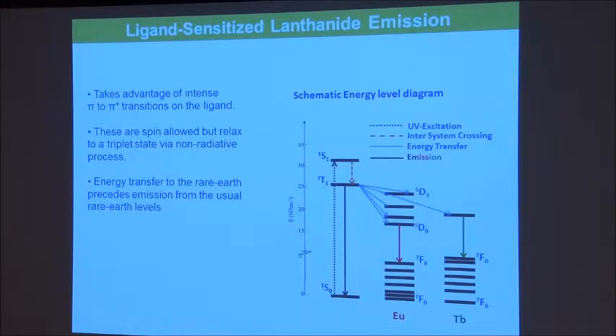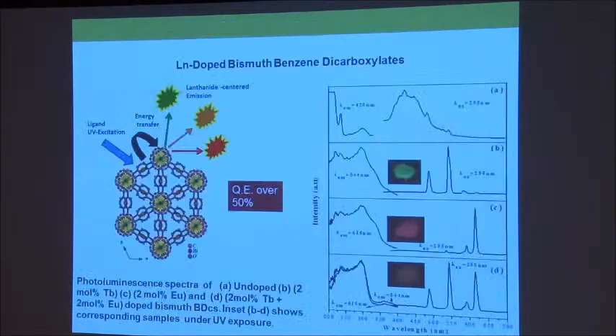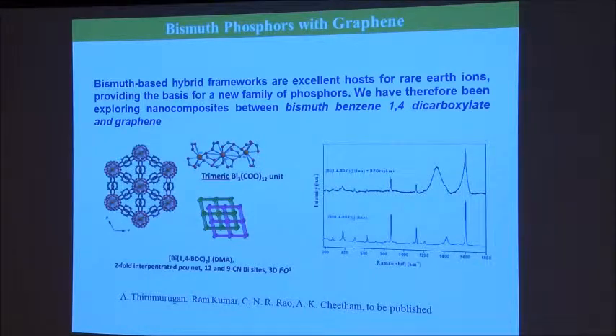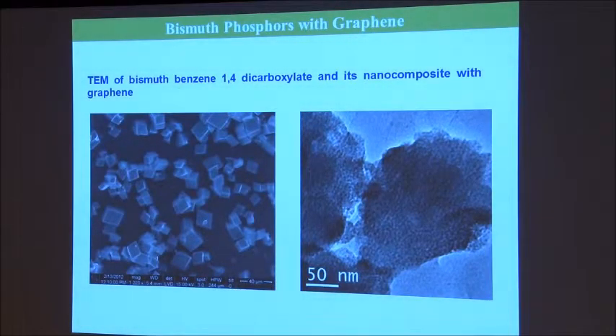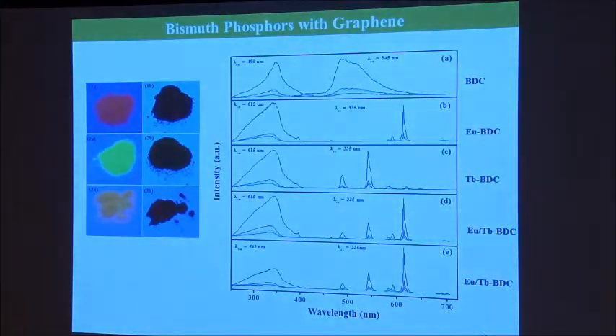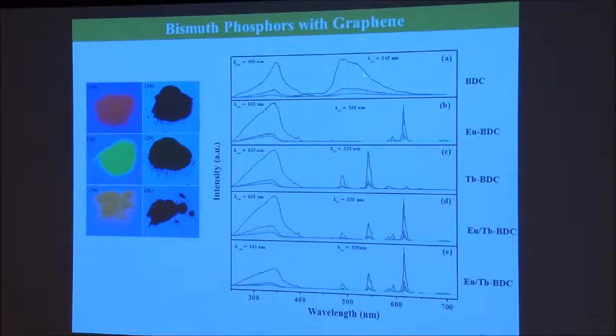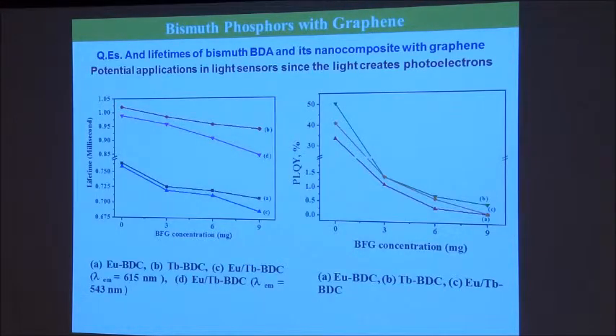We are also looking at optical properties, ligand sensitized lanthanide emission. In the case of bismuth compounds, these materials give wonderful colors with different rare earths. I can make graphene composites with these things, and you can make materials with all kinds of morphology. You can see the wonderful photo emission in the original rare earth doped material. As you go on putting graphene, the material quenches that, because this may have the ability to do tuning of the photo emission, tuning of the lifetime, and quantum yield using graphene composites.